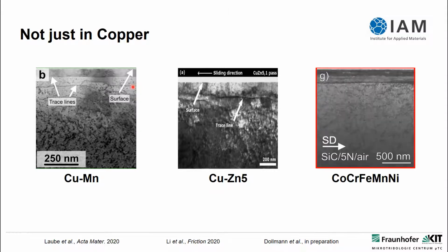We have also looked at, for example, a high entropy alloy like the Cantor alloy, cobalt, chromium, iron, manganese, nickel, where we also see a dislocation trace line, actually a really sharp, nice one. It depends heavily on the counterbody, but under certain conditions, when the plastic deformation is not too high and we don't get a lot of adhesive wear, we do see a dislocation trace line.